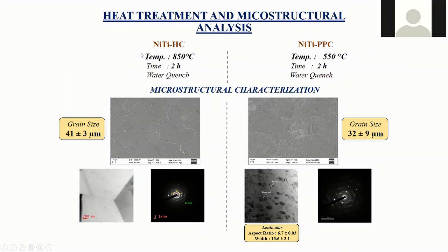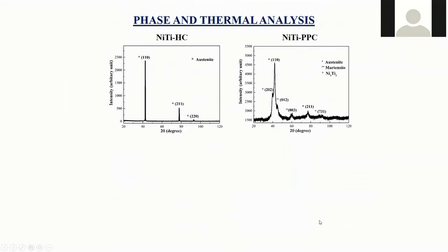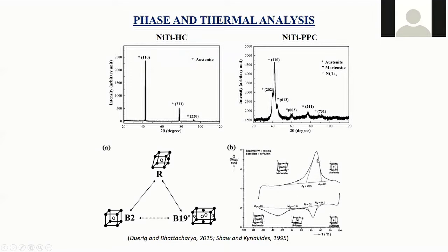So this is basically a solutionized alloy, and we also have the precipitated alloy. What we knew is that the precipitated one has different kinds of phases, like the martensite phase and the precipitate phase, even at room temperature. Now if we have this kind of precipitate phase, this is supposed to give us not only the austenite to martensite transformation, but there is an intermediate transformation through R phase.